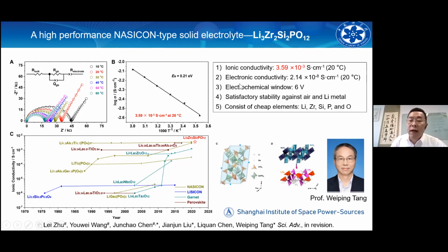And it has a very wide electrochemical window, and it's stable in air and also stable against the lithium and cathode. And also it does not contain rare earths. It only consists of cheap elements like lithium, zirconium, silicon, phosphorus, and oxygen. So this is a very promising new oxide electrolyte material, and we are trying to develop the related science of the solid-state battery.